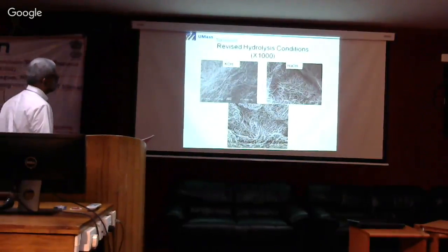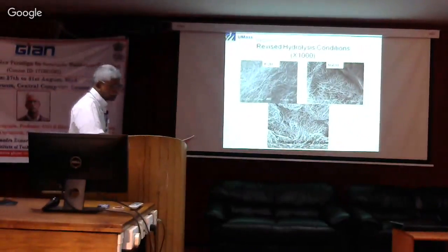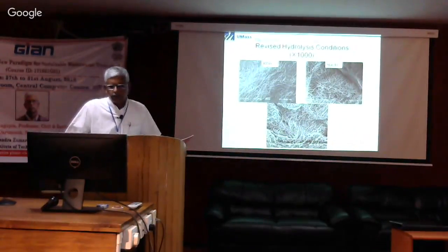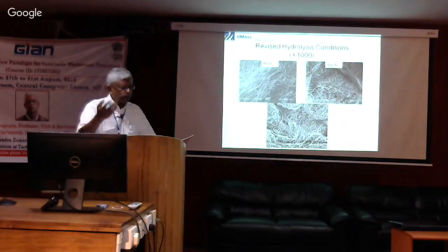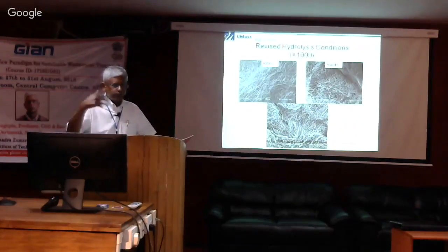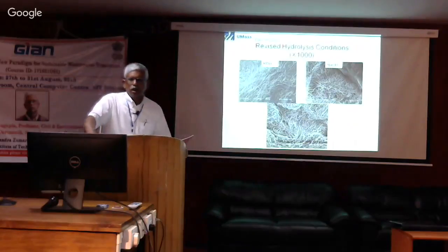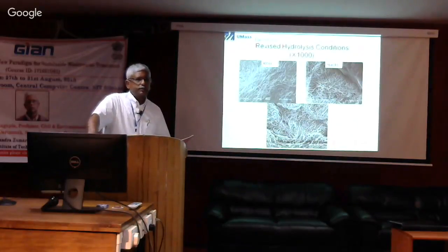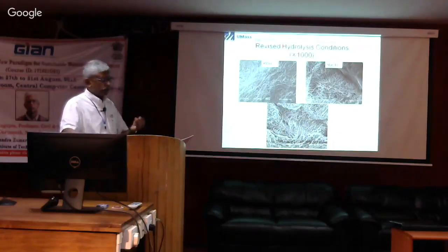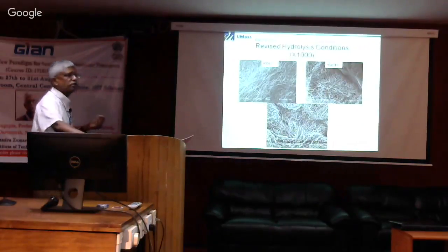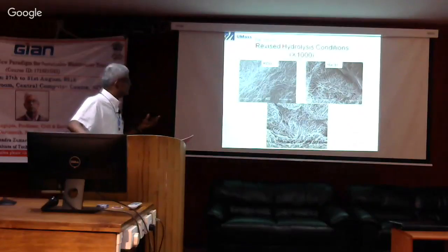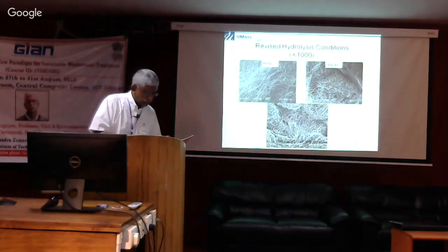Now, what is interesting about our research was that you get this fiber, functionalize it, and use it to do the ion exchange that you are planning to do. In this case, it was to remove copper. If this material becomes dry, it immediately powderizes. So there is some kind of a hydrogel formation going on. If you keep it wet, perfectly fine.